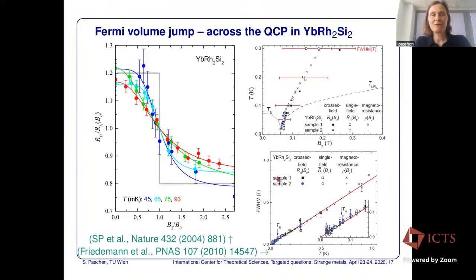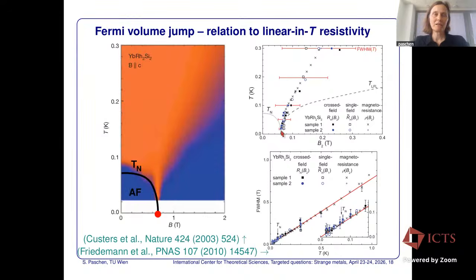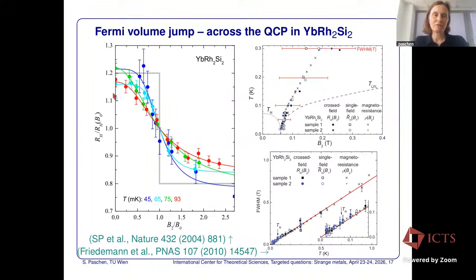So let me just show you a few of these evidences. I think the Fermi volume jump is an important one, so I show it again, even though that was our first new signature in addition to linear in temperature resistivity. So across the phase diagram where this strange metal behavior is observed, we have a crossover in the Hall coefficient that gets infinitely sharp, meaning its full width at half maximum extrapolates to 0 when we move towards 0 temperature.